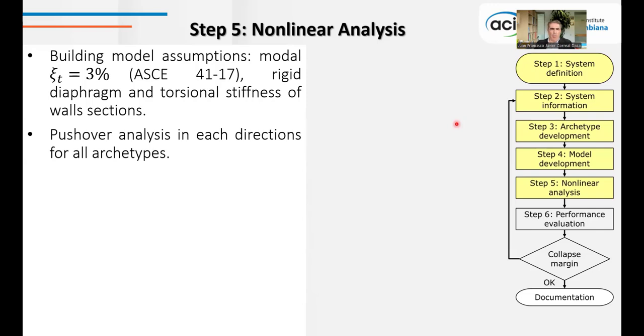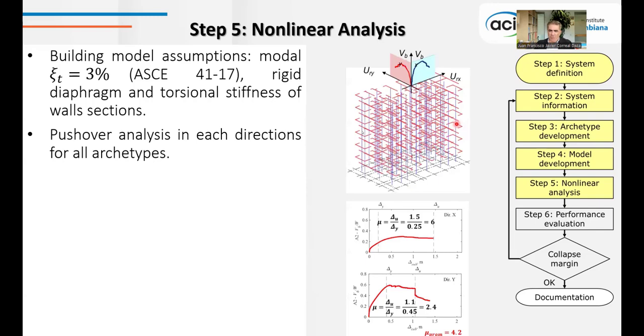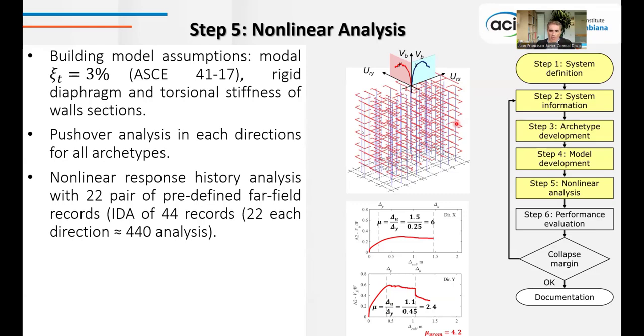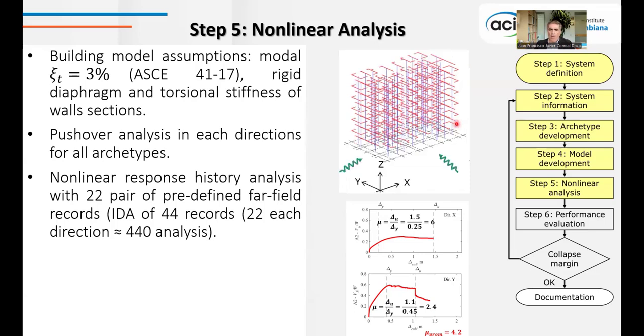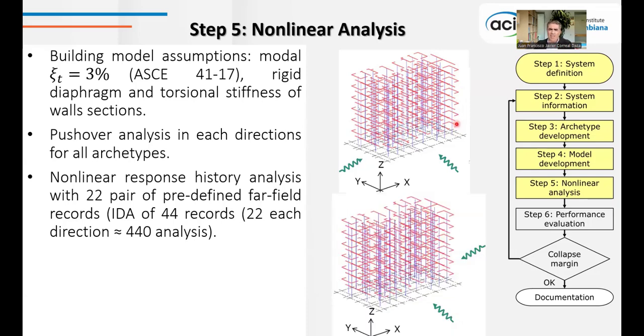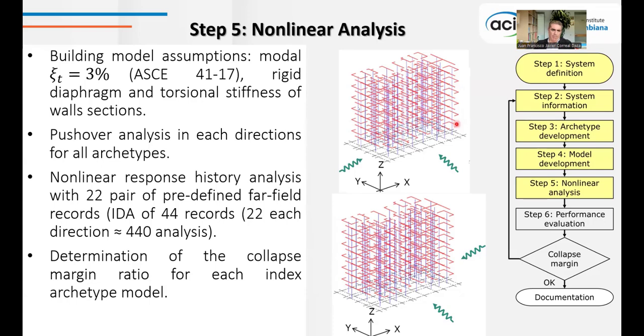Once we have the model ready, we perform a pushover analysis in each direction, as you see here in the picture, and then we take the average of the ductility capacity, which is data that we're going to use in step number 6. Then we perform a nonlinear response history analysis with the 22 pairs of predefined far-field records that the methodology implies. In other words, we perform an incremental dynamic analysis of 44 records because we have to apply 22 in each direction. In total, it gives us around 440 analyses per archetype.